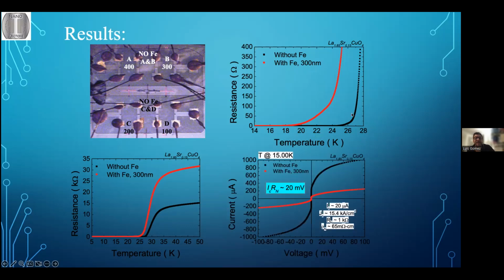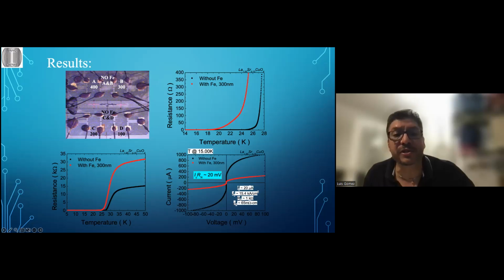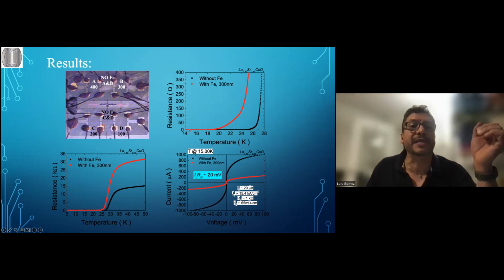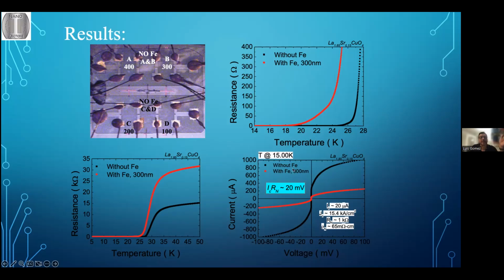And then after we choose a particular value of temperature, in this case right here at 15 Kelvin, this curve is the current-voltage characteristic at 15 kelvins, which is somewhere around here. So it's fully superconducting. The sample that has either no iron or iron, both are fully superconducting, but the IV characteristic is completely different.